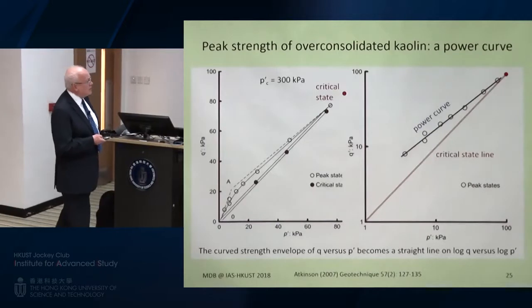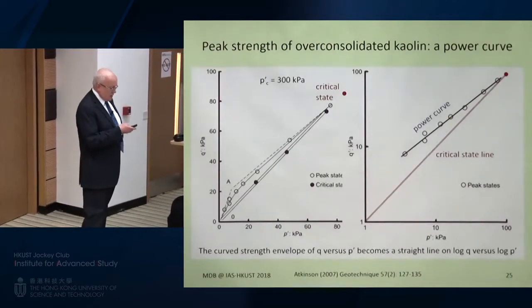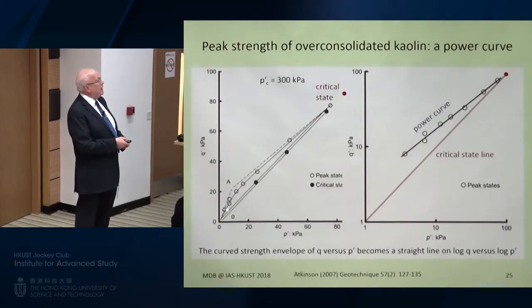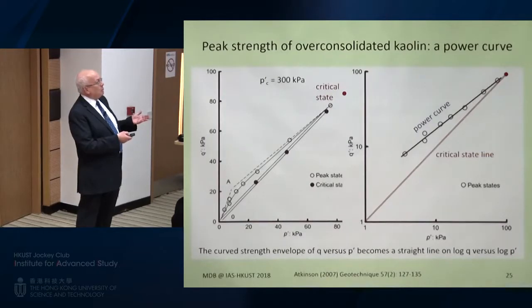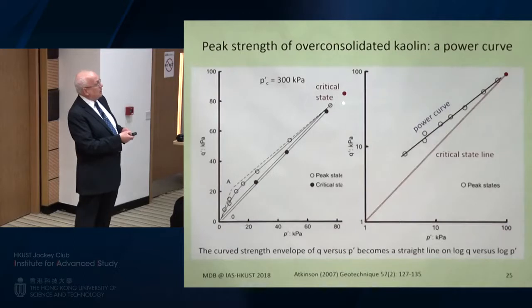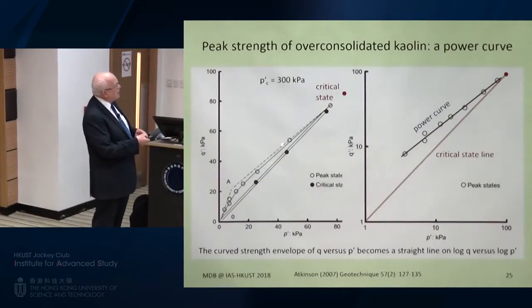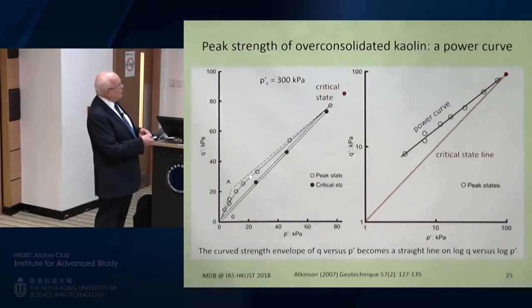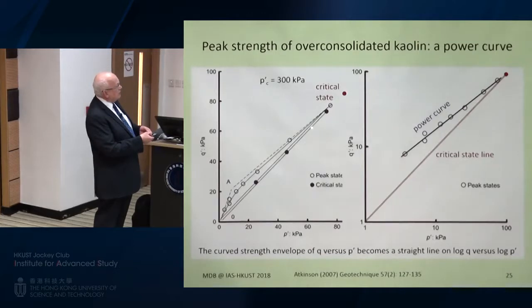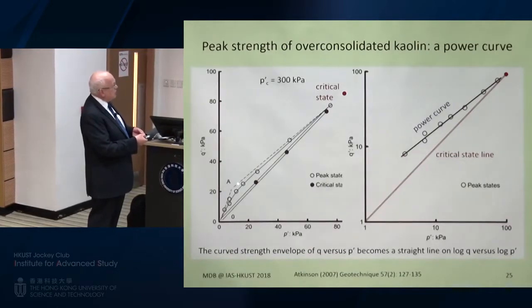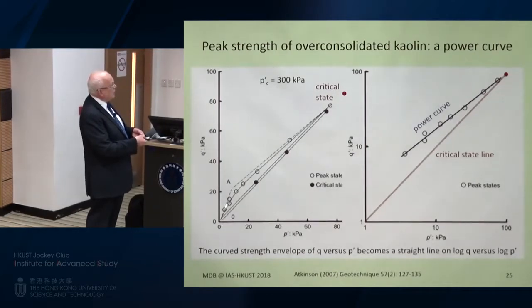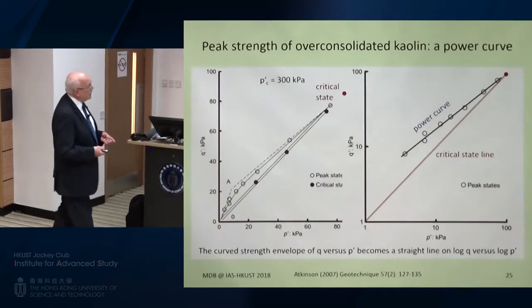Anyway, here's the data of John Atkinson, to whom you go for nice data on clays. And this is the similar plot of, in this case, clay pre-consolidated, I think, to 300 kPa. Can't quite remember now. But anyway, here is the data of critical states, which are the post-softening data. Here's the peak strength data, and he puts a curve through it, and then, for some reason, wanted to draw a linear Mohr-Coulomb envelope, but then drew a 3-on-1 line for tensile fracture.